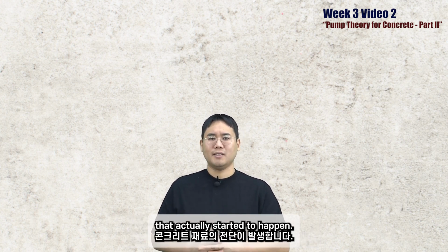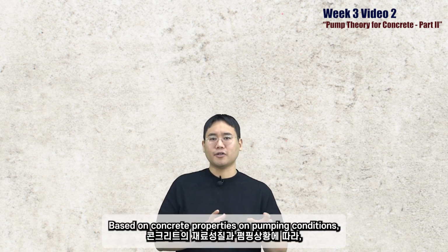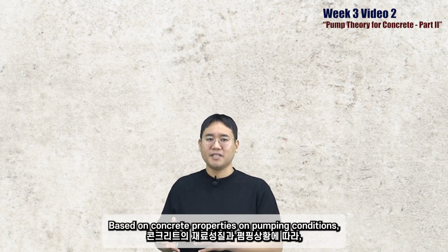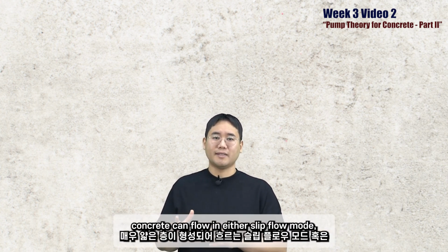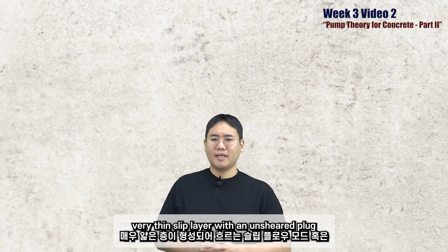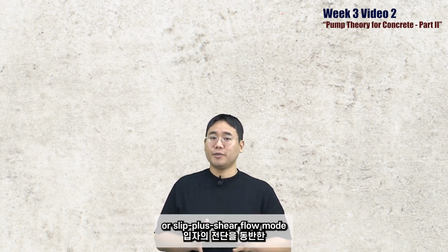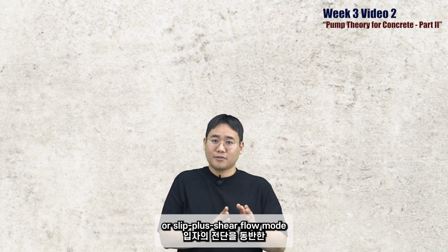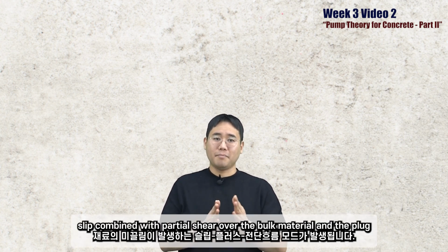Based on concrete properties and pumping conditions, concrete can flow in either slip flow mode, a very thin slip layer with an unsheared plug, or slip plus shear flow mode, slip combined with partial shear of the bulk material and the plug.